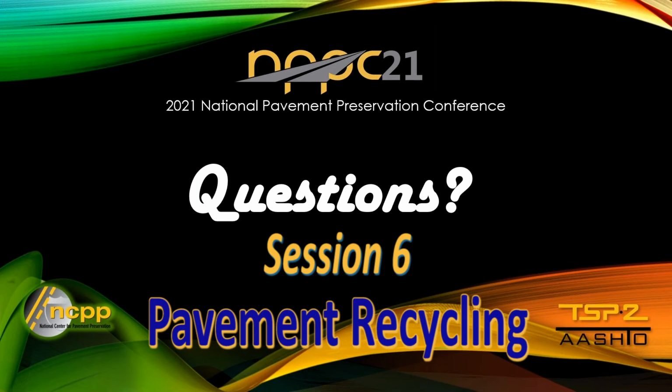I'm going to just add one: if it's an emulsion chip seal, typically it's not a problem. We have had some issues with an asphalt rubber chip seal that had a little issue of gumming on it. A couple projects we just recycled through it. A couple projects though, we actually found the gumming was so much we removed the chip seal, but that was only when it was an asphalt rubber. If it's an emulsion chip seal, we don't worry about it in CIR.